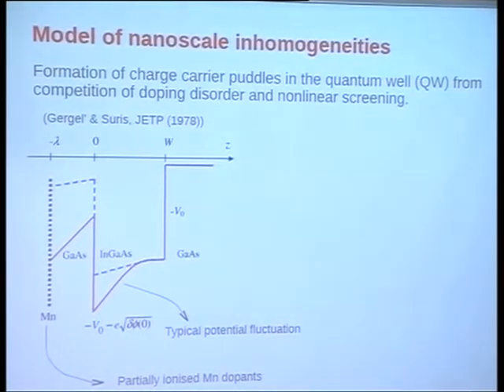So here is very simple-minded modeling now. We essentially follow Gergel and Suris and many other people after that, and just use that kind of phenomenology for such devices, and rough numbers we obtain from experiment, from people who grow the devices and from measurements. So this is how it crudely looks. Here's the Mn dopant layer. It's separated from the left side of the quantum well by a distance lambda, and you have a quantum well of thickness W. In our case, this is about 10 nanometers, and this is 3 nanometers.